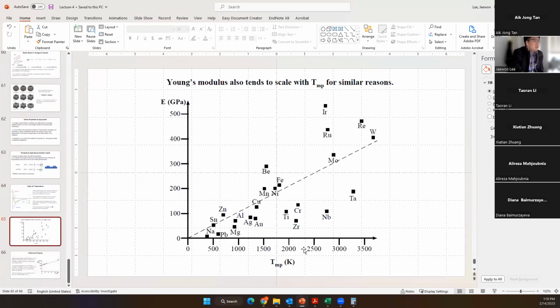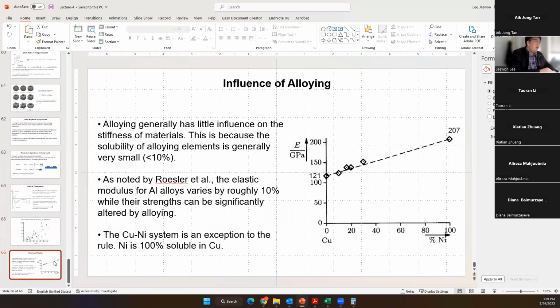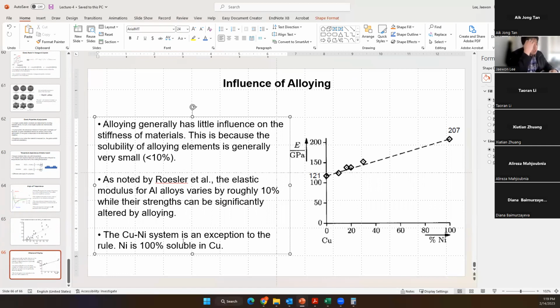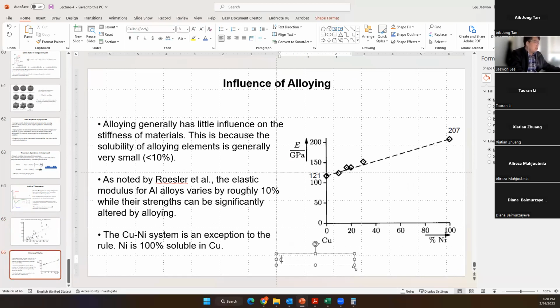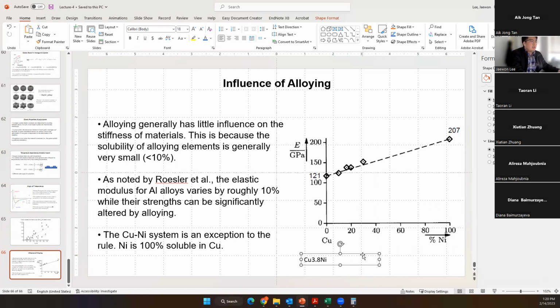This is the melting temperature of the materials and Young's modulus. It follows a very similar trend, almost a linear relation. However, alloying elements cannot improve the stiffness significantly because they cannot be mixed completely. However, in the case of the copper nickel system, they can be mixed easily. Because of that, they can increase the elastic modulus because they mix together very well.